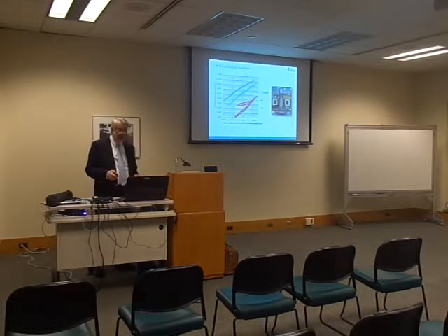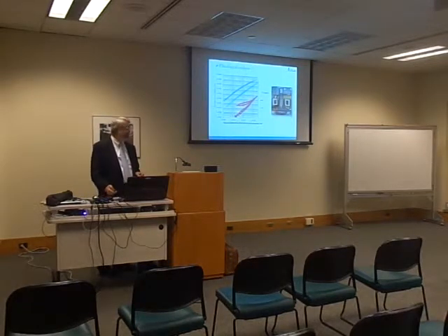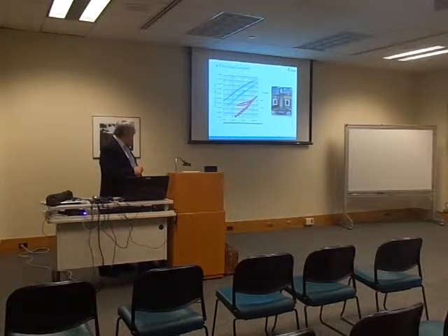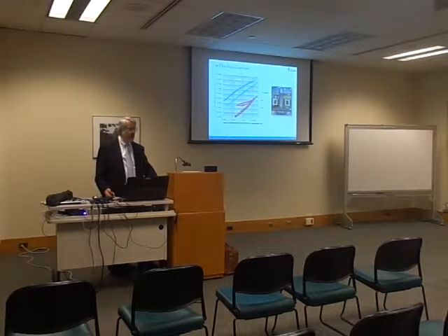For those of you who are familiar with complex moduli and frequencies and this and that, you'll tell immediately that the rejuvenator for this particular case is a liquid, for the mere fact that it doesn't plot nicely in this plot. Okay, now we know it's a liquid. We knew it because we put it in, but it's nice to prove the theory right.